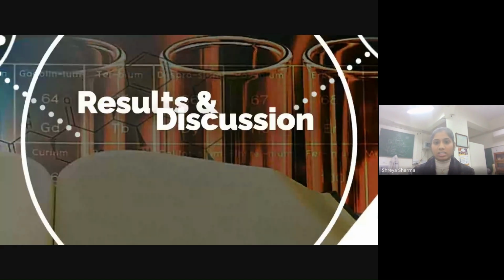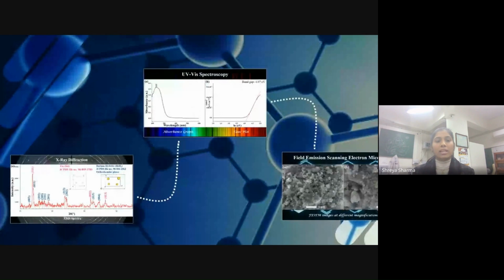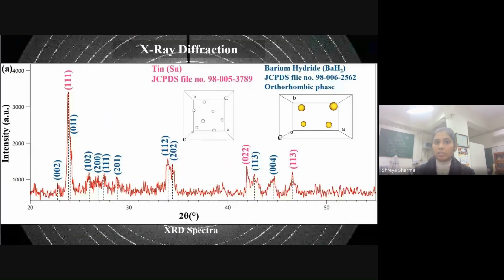Now going on to the results and discussion part, I'll start with the structural analysis of the material, which was done by the X-ray diffraction technique. Here we can see the XRD pattern of the as-synthesized material in which high-intensity peaks can be observed. It reveals the crystalline nature of the material. The peaks were matched with barium hydride of the orthorhombic phase with the JCPDS file number as shown on the right-hand side, and some peaks were matched with tin as indexed with the JCPDS file number shown here.